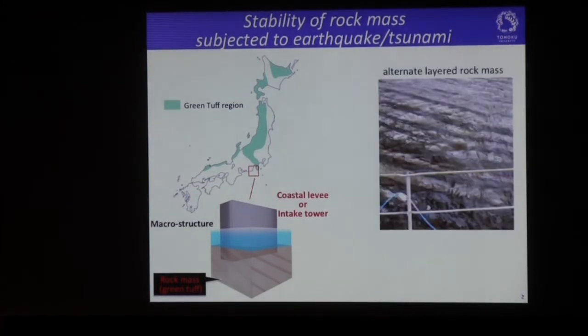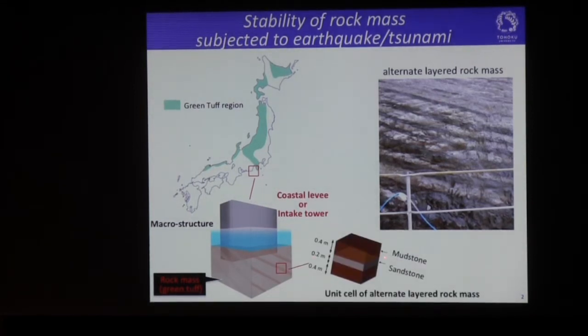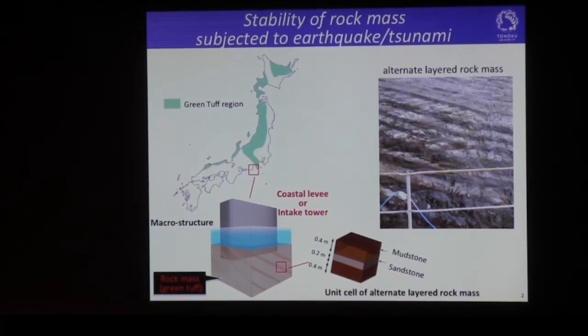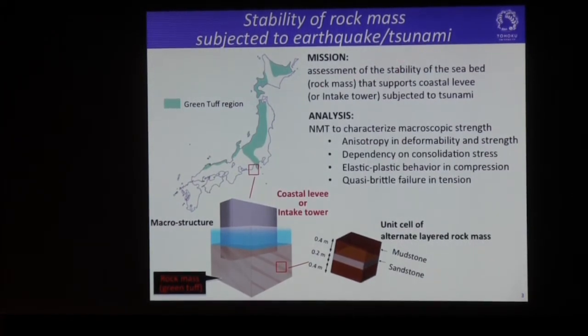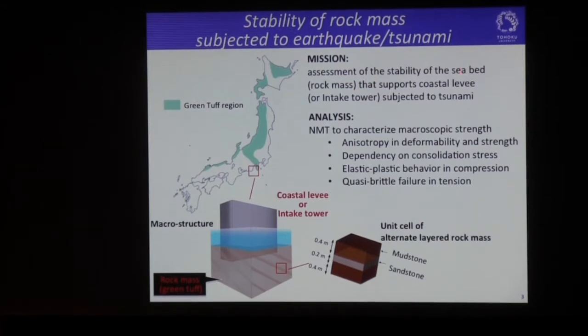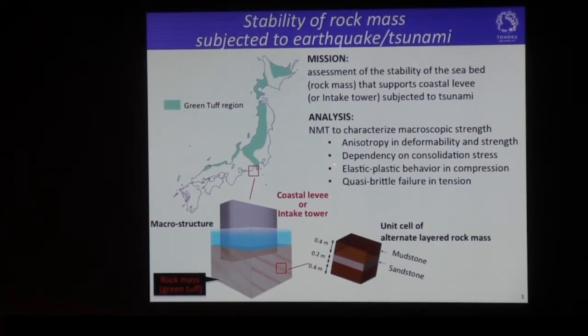This coast is covered by this kind of alternate layered rock mass, which has this kind of microstructure, composed of mudstone and sandstone. This is the microstructure, although this has this dimension here. So the mission is to assess the stability of the seabed, that is the rock mass, that supports the coastal levee or intake tower subjected to tsunami. For that purpose, we have to conduct a numerical material test to characterize the macroscopic strength by considering the anisotropy in deformability and strength, and also we'd like to consider dependency on the consolidation stress. At the same time, we consider the elastoplastic behavior in compression and also the quasi-brittle failure in tension.